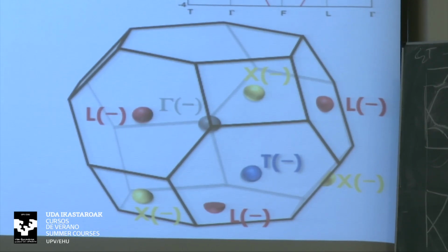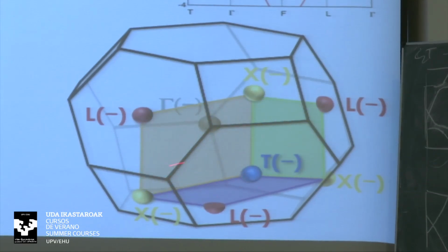So bismuth is not a strong TI, and the weak indices are coming from multiplying these signs along these three planes, which are just normal to the primitive vectors. So it doesn't have weak indices either. So this doesn't seem to support bismuth being a weak topological insulator and any mode plunging into the screw dislocation.